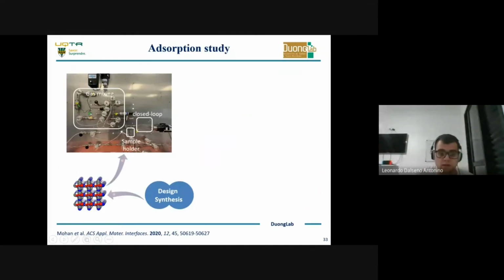This is the instrument that my student is using to do the adsorption study. After synthesis, and after defining the structure and the texture of the materials, they use this instrument to do the gas adsorption study. The sample you put here, and then you have a closed loop, and you can mix the gas here and then study the adsorption.